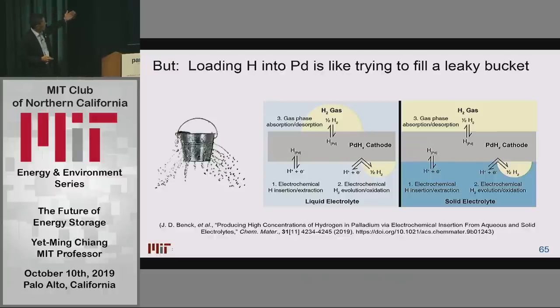We can do that, but the problem is that hydrogen leaks out of palladium just as fast as you put it in. That's why you can't get this stuff loaded to a very high state. So we have the problem of electrochemically pumping in hydrogen easily, but it leaks out very quickly. So how do you stop the leak? That essentially turns out to be the problem.